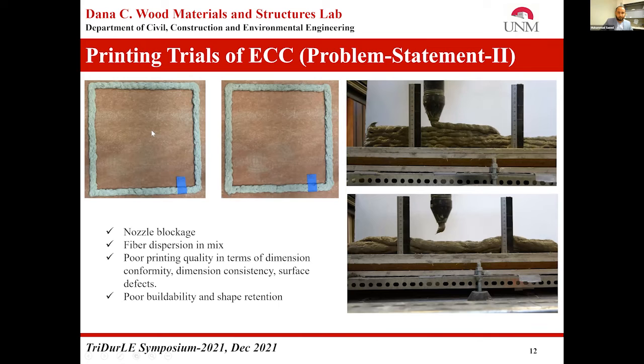In the initial printing trials on these ECC mixes, we faced many challenges, because printing ECC is difficult: due to the high content of fiber, it can block the printing nozzle, and fiber dispersion in the mix is another issue. We got very poor quality in terms of extrudability. As you can see, the printed filament doesn't have good dimension consistency and conformity, and the surface quality is also not good. If we look at the buildability and shape retention, most of the mixes collapsed after printing a few filaments.